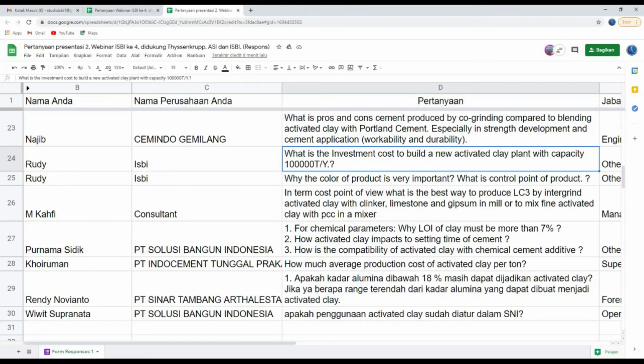Okay, then there's the question on the chemical parameters. LOI, why must it be higher than 7%? At the end, this value only gives us an indication of whether there is some clay in it or not. If we are talking about kaolinitic clays, there must be a certain minimum of kaolinite within the clay. This LOI of around 7% indicates that there is a mineral in this clay, especially kaolinite, which then contributes to the strength development. So this LOI is just giving us the indication that there is a suitable clay in it.